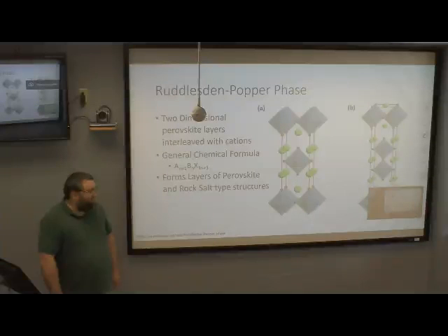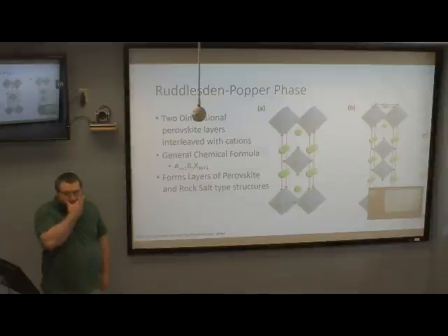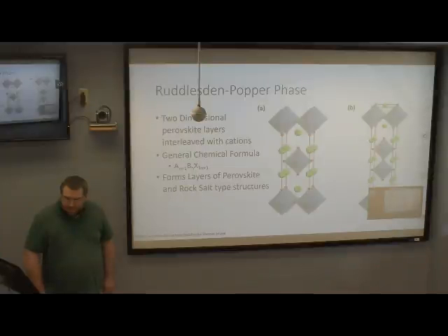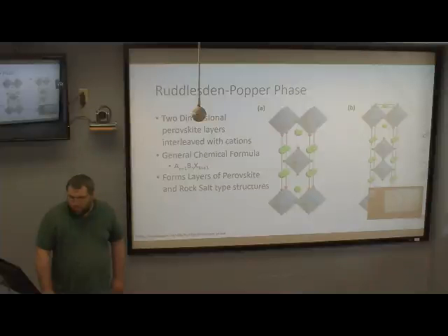I need to come up with a good answer for your question. If you try to play logic, is it possible to create two-dimensional perovskites which will not be of the Ruddlesden-Popper phase? Yeah, but it will be another exotic phase. So you are not bringing new stuff. You're just digging deeper into two dimensions, and you are claiming that if one tries to synthesize two-dimensional perovskites, they naturally, highly likely will be in this Ruddlesden-Popper phase.